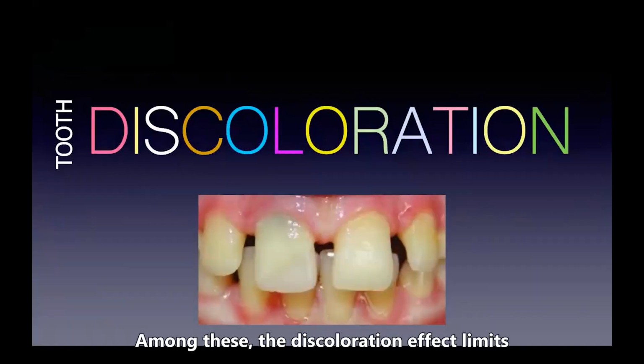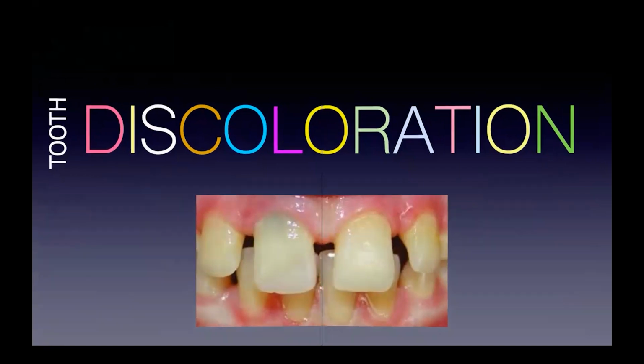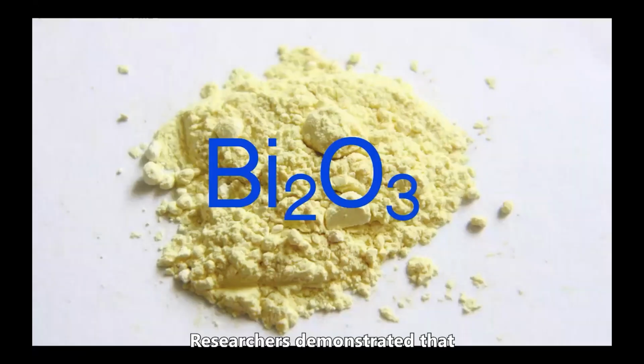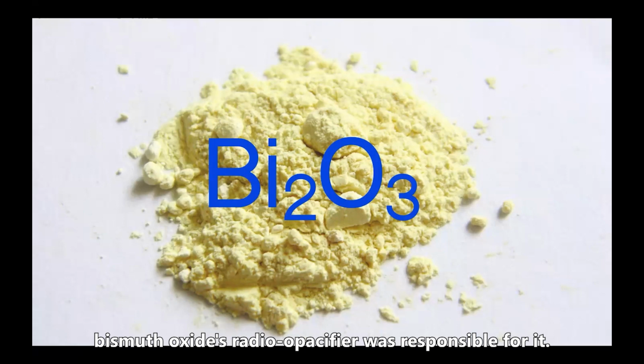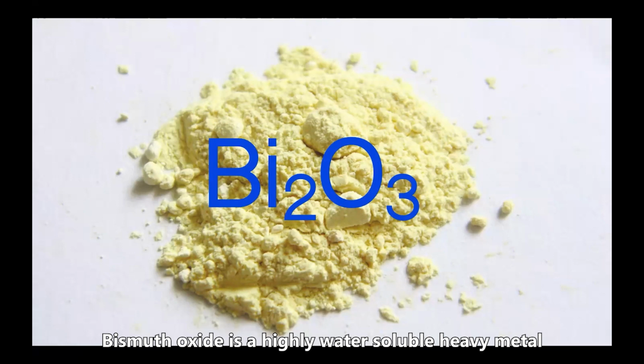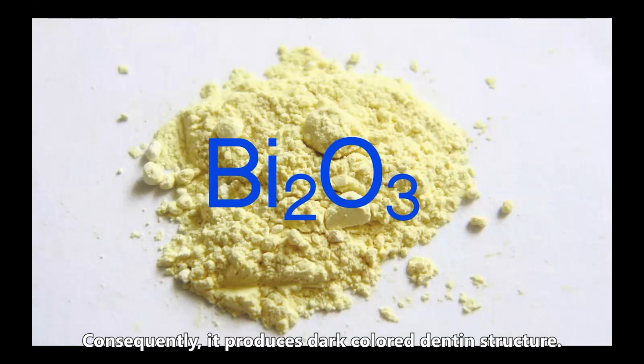Among these, the discoloration effect limits its application to the anterior teeth. Therefore, researchers tried to find the cause of the discoloration and finally found it. Researchers demonstrated that bismuth oxide, the radiopacifier, was responsible for it. Bismuth oxide is a highly water-soluble heavy metal, and it can be bound with collagen fibers in the dentin matrix easily. Consequently, it produces dark-colored dentin structure.